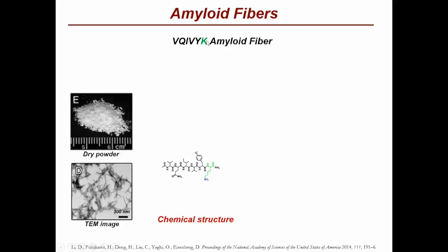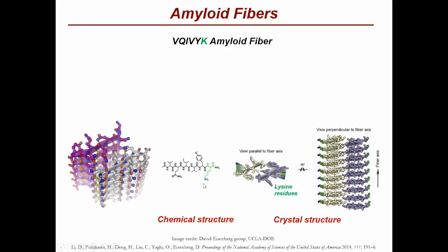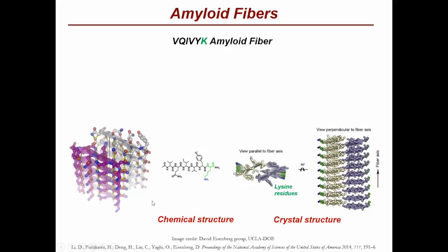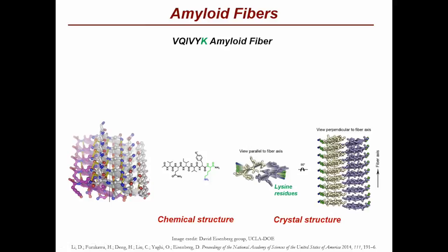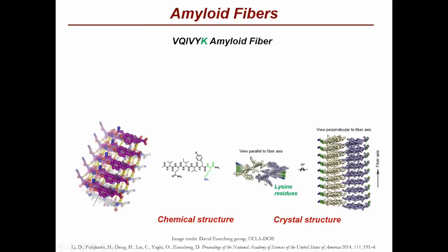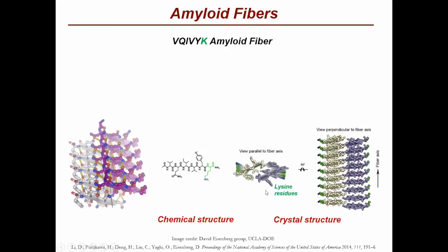The K peptide here, also known as lysine residue, is highlighted here in green. And the amino group of the lysine is what is responsible for carbon dioxide capture. If you look at the crystal structure of these fibers, they have parallel beta sheets, which are held together by hydrogen bonding interactions. The side chains of these peptides have strong steric zipper-like interactions, which make these fibers stable, stiff,